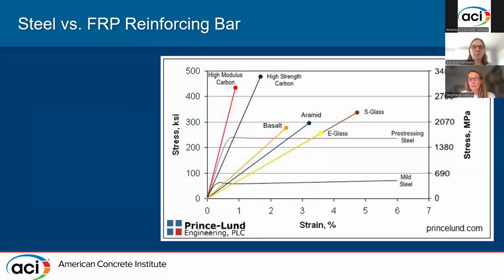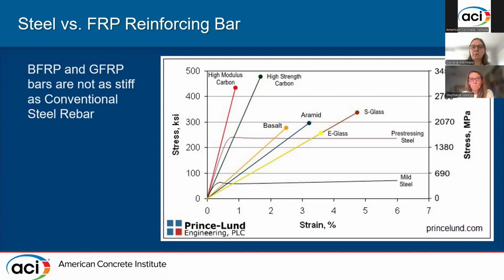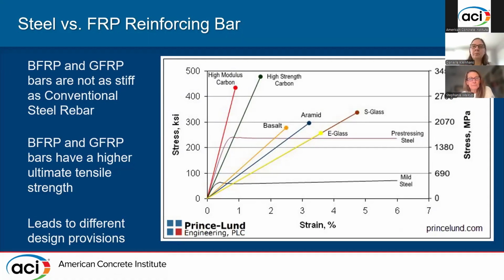When we compare the bars, and here we're showing basalt, aramid, glass bars as well, along with carbon bars, to our pre-stressing steel or mild steel, we can see that the basalt, aramid, and glass bars have a smaller modulus of elasticity, where they're not as stiff as steel bars. However, they have a higher tensile strength. Carbon matches approximately the modulus of elasticity of traditional steel bars, but has an even higher tensile strength than our basalt, aramid, and glass bars. As a result of these different material properties, we have different design provisions, and that's what prompted the development of ACI code 440.11-22.